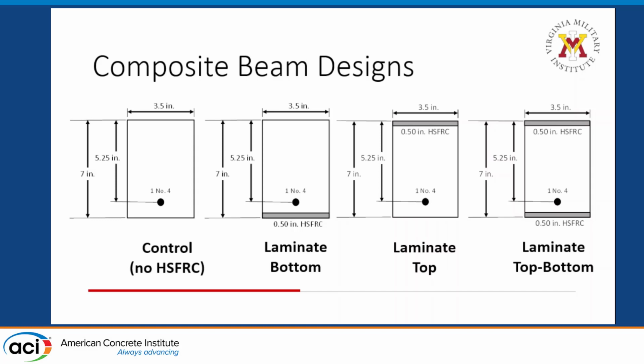The overall footprint of these beams was a 3.5 inch width, 7 inch depth, and 7 foot length. We had one number 4 reinforcing bar located at a 1.5 inch clear cover from the bottom of the normal concrete section, and all the laminate thicknesses were 1/2 inch. And we had 3 of each type of these beams for a total of 12.